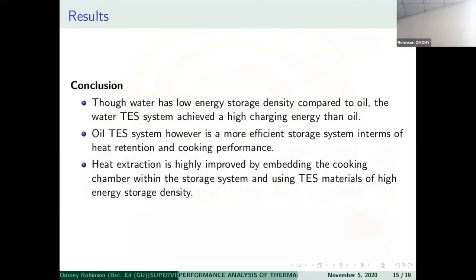Then in conclusion, we arrived and said, though water has low energy storage density compared to oil, the water TES system achieved a higher charging energy than oil. And the oil TES system, however, is a more efficient storage system in terms of heat retention and cooking performance. And we also concluded that heat extraction is highly improved by embedding the cooking chamber within the storage system and using TES materials of high energy storage density.